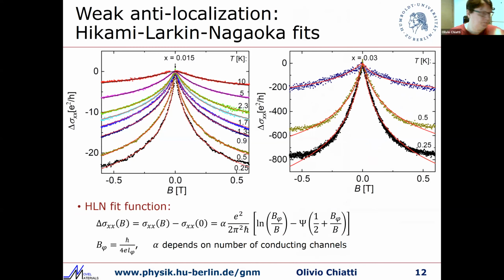Having now dips in the magnetoresistance, we can apply the Hikami-Larkin-Nagaoka fit to extract some data like the phase coherence length. And we use a typical fit function for two-dimensional systems with a strong spin-orbit coupling. And the fit parameters are the parameter alpha, which depends on the number of conducting channels, and this parameter B_phi, which depends on the phase coherence length.